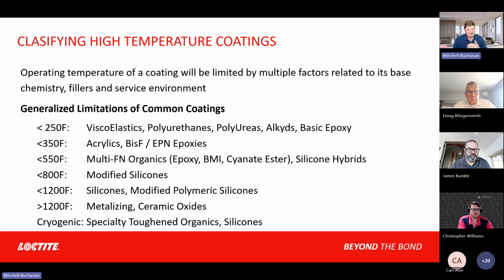And then also as a tidbit, which is the opposite end of this spectrum, is going to be cryogenic coatings, sub-freezing coatings. Some of this is important in the pipeline industry, but also aerospace, space applications, right? A lot of your silicones that are in that 1200 Fahrenheit range also do very well down to cryogenic temperatures. And then when you look at that negative 100 F or C type situation, you can get organic coatings like epoxies down to that temperature, but they're going to be using very specialized high-end cold temperature tougheners that have very good flow properties below negative 50 F.